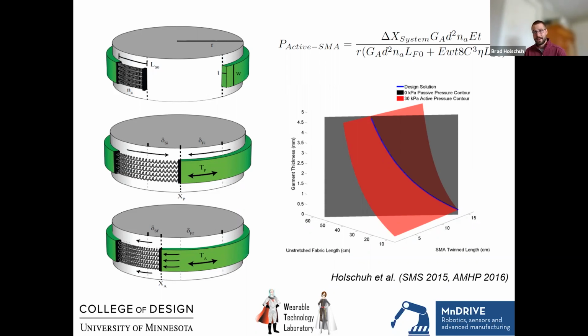And then as the actuators contract, it creates a stress and therefore a strain and an extension in the passive fabric. And ultimately you end up at an equilibrium state where there is a captured tension around the circumference. And if you're trying to, for example, produce compression, which is what we cared about in the spacesuit example, you now have controllable compression. You have, in effect, a tourniquet that you can create varying amounts of squeeze depending on how hot you're willing to get those actuators and how much power you can supply to them.